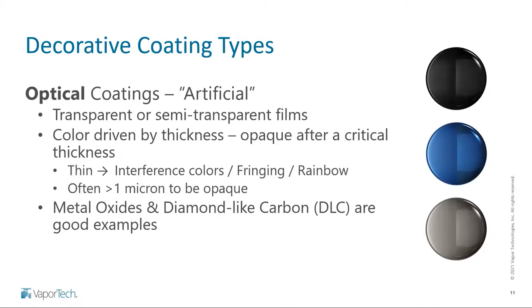The other type, when I was talking before, I mentioned artificial coatings, which may not be the most natural looking ones. These tend to be made by optical approaches, where these coatings can be transparent or semi-transparent, meaning that the color is often driven by the thickness. If it is below a critical thickness, you can get some interference colors, some rainbows, or some of these vivid colors like these vivid blues that come from an interference effect. But once you get above a certain thickness where all of the light is getting absorbed by the coating and no more is getting reflected from the undersurface, it will then become opaque. But it takes a much thicker layer before it becomes opaque, sometimes as much as a micron thick. And this is common for things like metal oxides and diamond-like carbons, DLCs. Those are good examples.